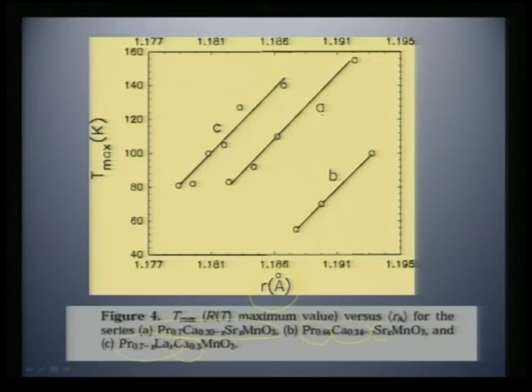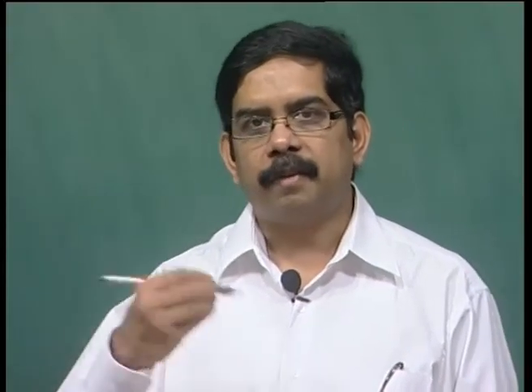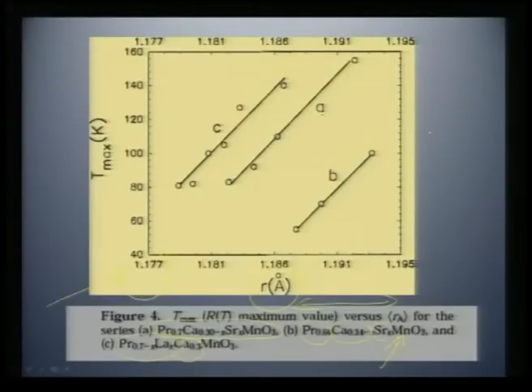So, it is not just necessary that you play around in this domain where the values are low, because you are essentially trying to disturb the Mn3+ to Mn4+ ratio there. So, what is so critical here in this R factor is that magic value of 1.17. When you are trying to make new compositions, always have two things in mind. One is you should always have an Mn4+ ratio of approximately 30%, and you should have your average A size value always above 1.17 angstrom.